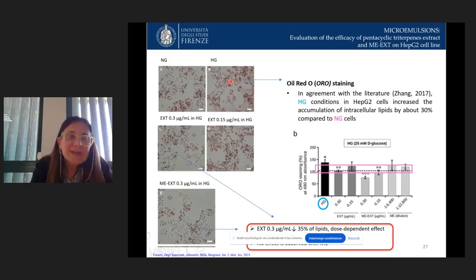And when we apply different concentrations of a triterpene extract on the cells with a high amount of lipids, we observe a reduction of lipid accumulation. In particular, this reduction is a dose-dependent effect, and in the case of the extract at 0.3 microgram per milliliter, we have a reduction of about 35% of lipid accumulation. If the extract is formulated in microemulsion, as shown in this figure, we have a reduction of about 50% of the lipid accumulation. With the same amount of the extract, but in the presence of the emulsion, the efficacy of the extract is improved. This is due to the presence of the constituents of the emulsion that improve the penetration of the extract inside the cells.